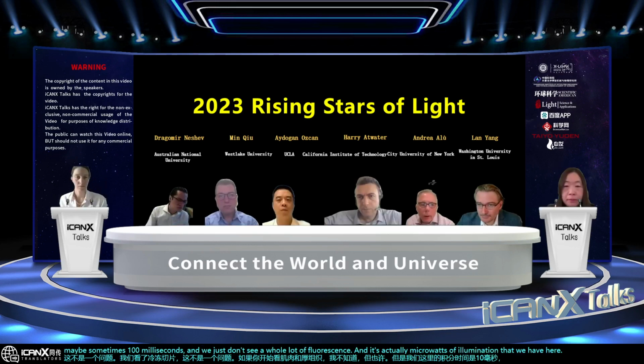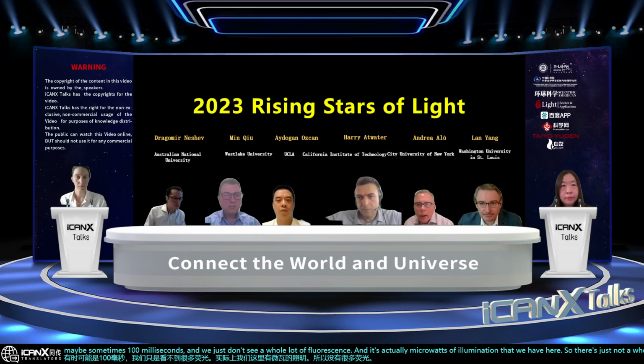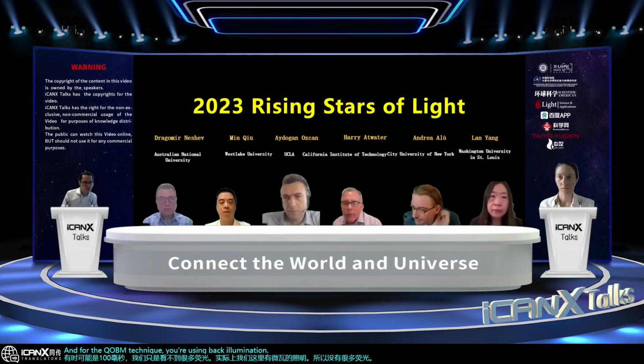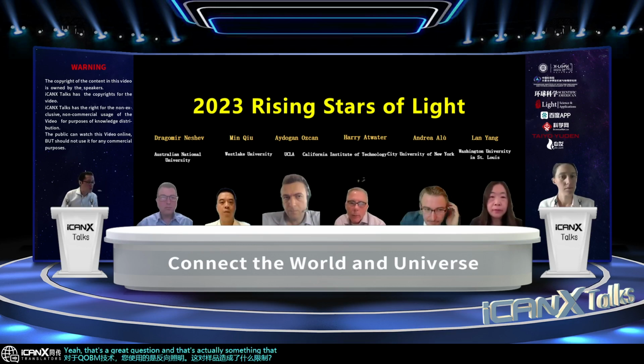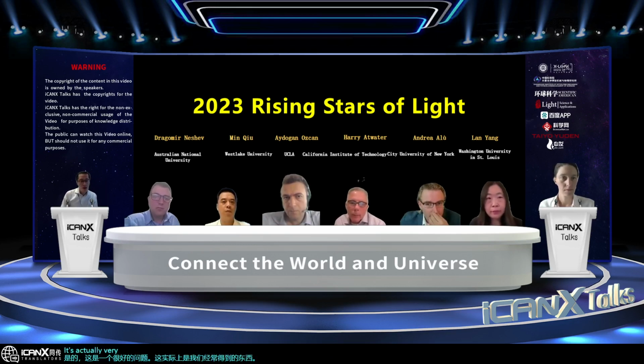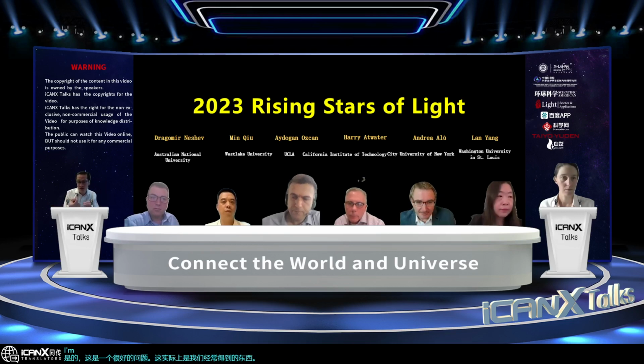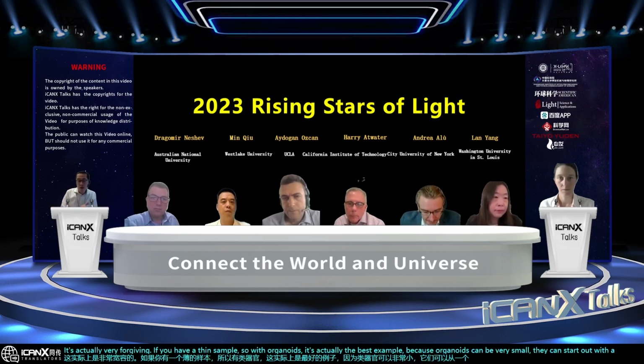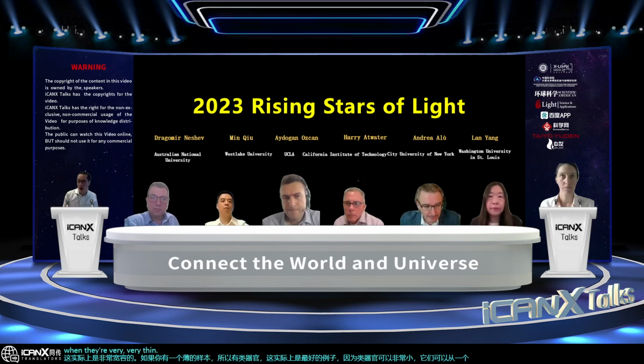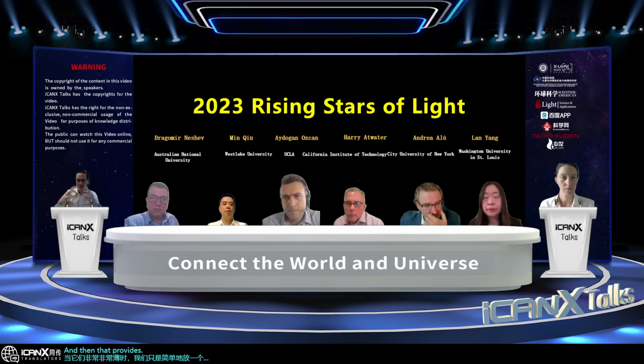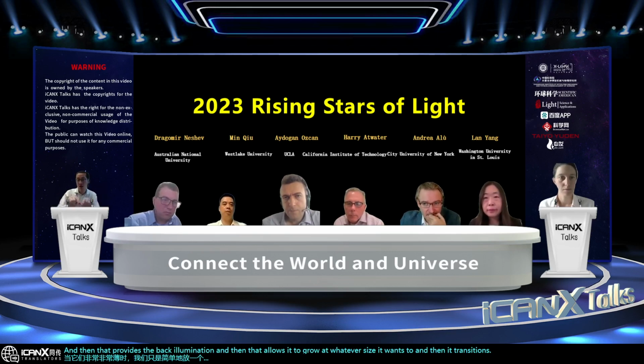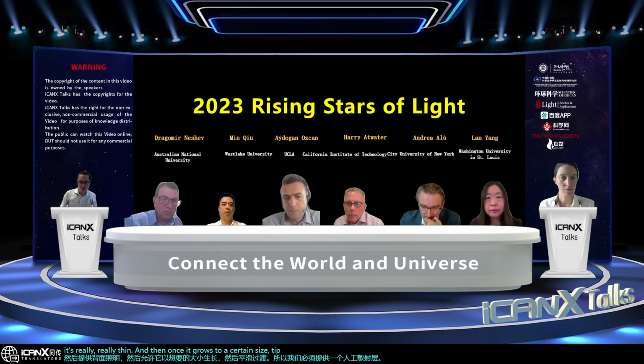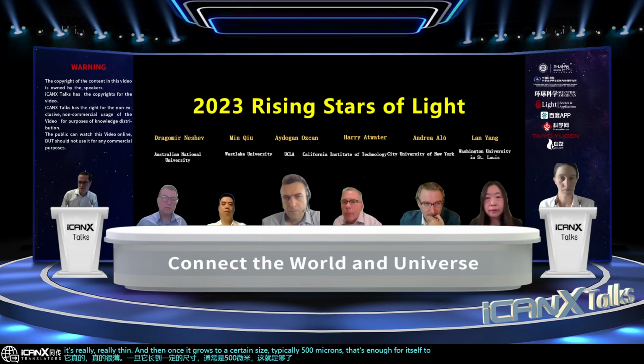For the QOBM technique, you're using back illumination. What limitations does that pose for the sample thickness? Yeah, that's a great question, and something we get very frequently. It's actually very forgiving. Organoids are the best example, because they can start out at around 100 microns in diameter and grow to be millimeters, right? When they're very thin, we simply put a scattering medium on top, which provides the back illumination, and then it transitions smoothly as it grows. So we provide an artificial scattering layer if it's really thin. Once it grows to a certain size, typically 500 microns, that's enough to produce the back illumination itself. I was thinking about the opposite limit, where you have a thick tissue.